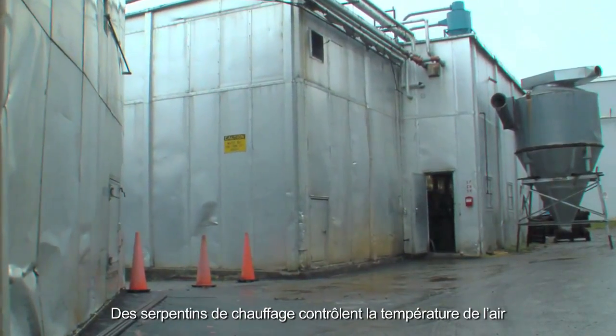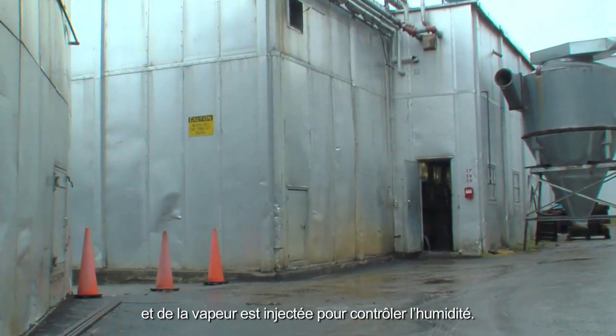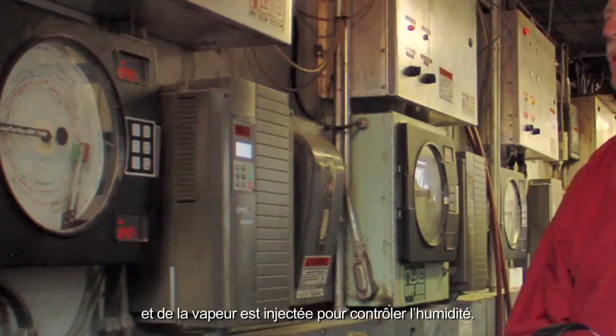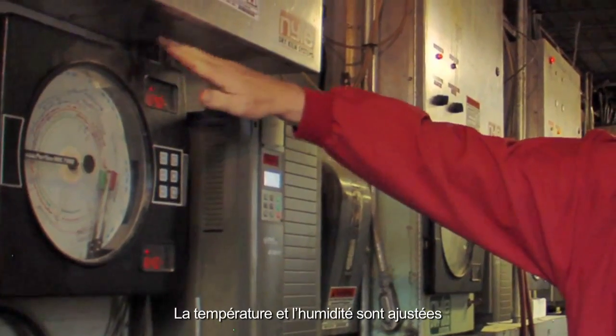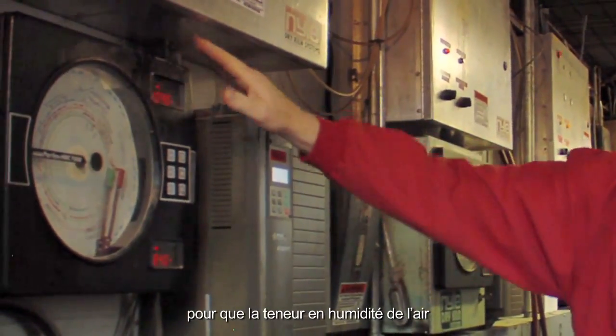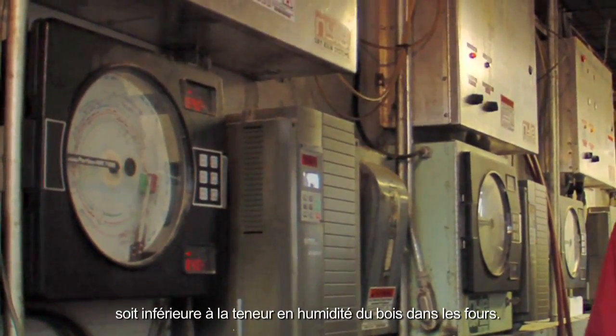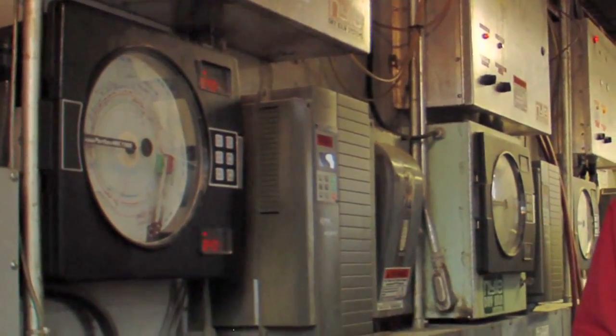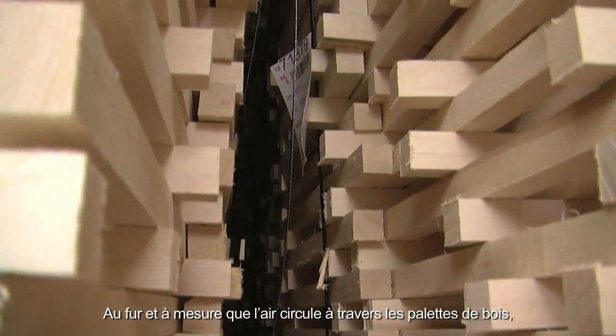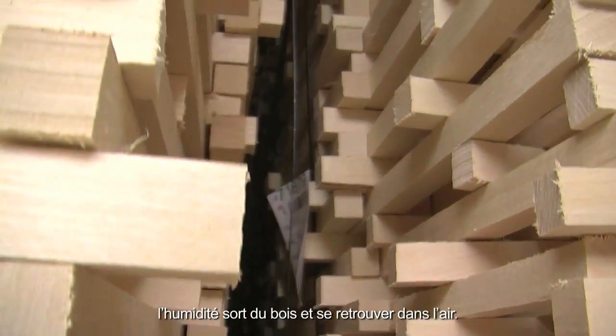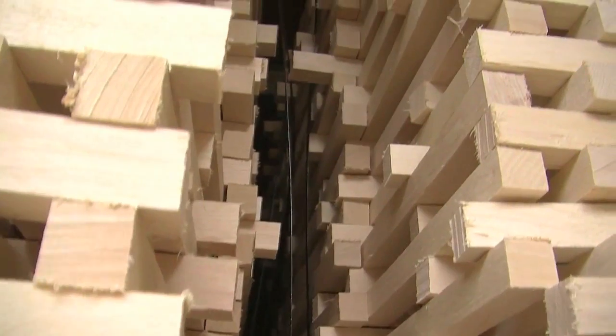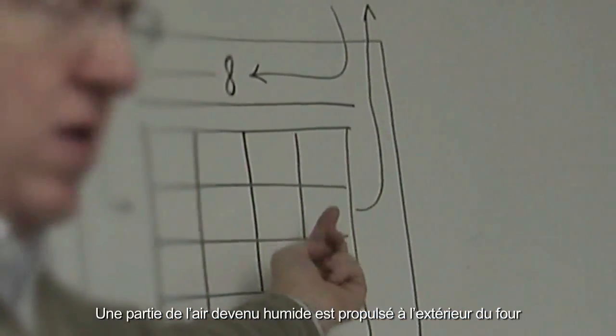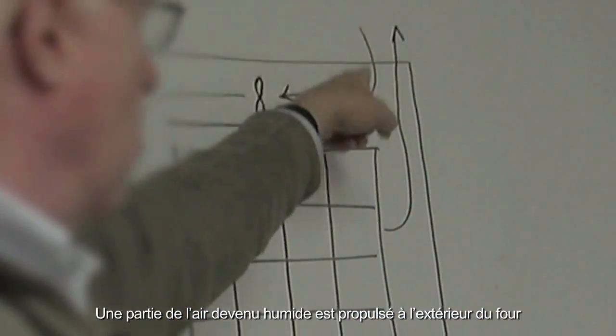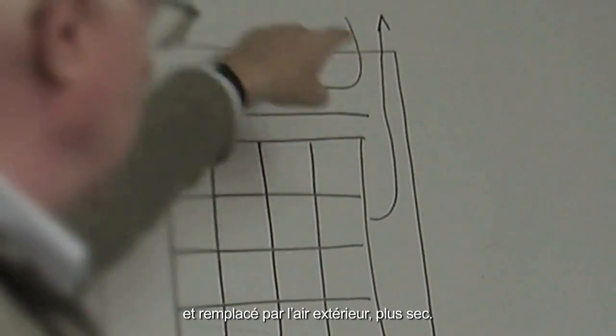Heating coils control the temperature of the air, and steam is injected to control the humidity. The temperature and humidity are adjusted so that the moisture content of the air is lower than the moisture content of the wood in the kiln. As the air passes through the stacks of wood, moisture migrates out of the wood into the air. A portion of the now wet air is forced out of the kiln and is replaced by drier outside air.